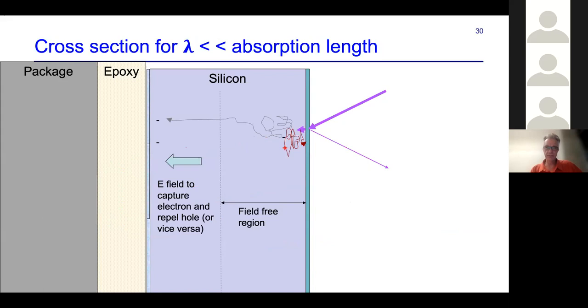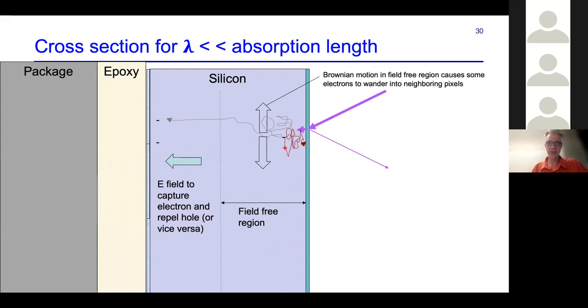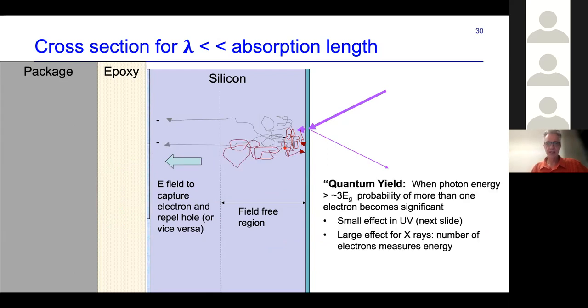So when the wavelength is very short, we can run into a second effect, which is that the charge can wander transversely before it finds its way into the electric field and the pixel. And so we would like to minimize that. And another thing that happens is that if we have enough energy, we can in fact generate more than one electron per photon. And it requires a bit of thinking to decide whether or not this is a bad thing or a good thing.